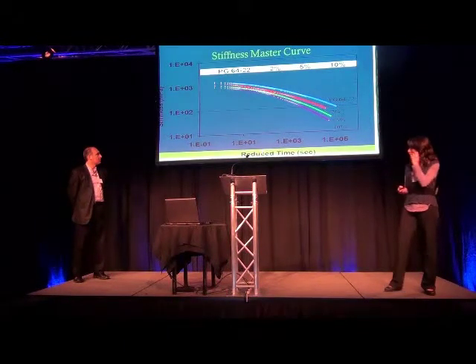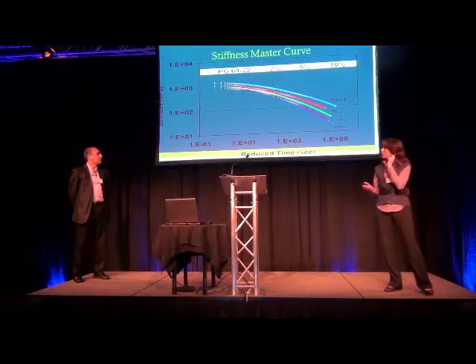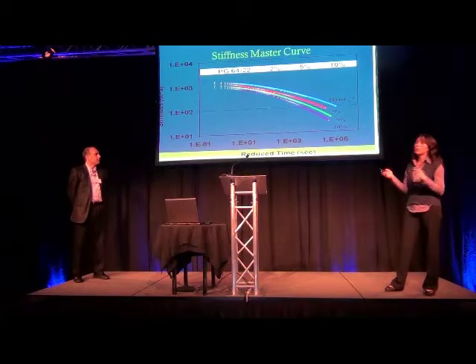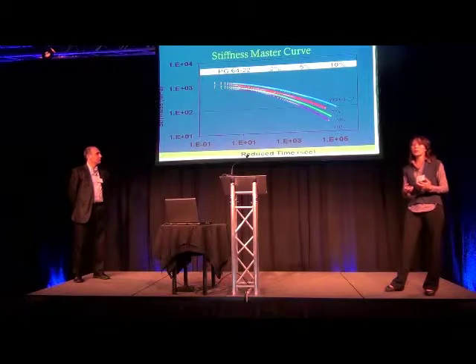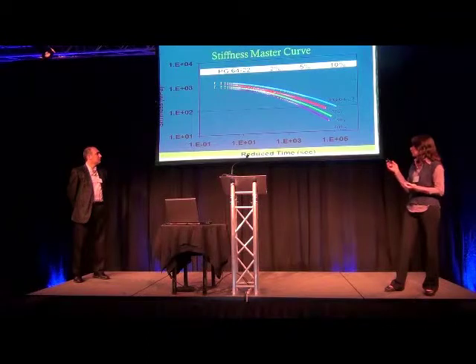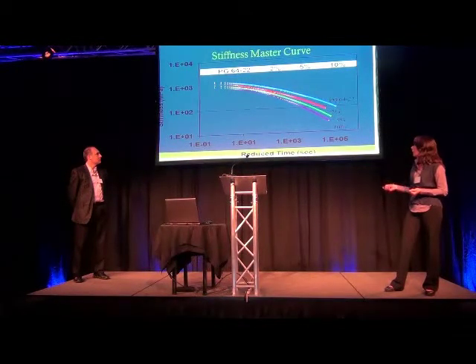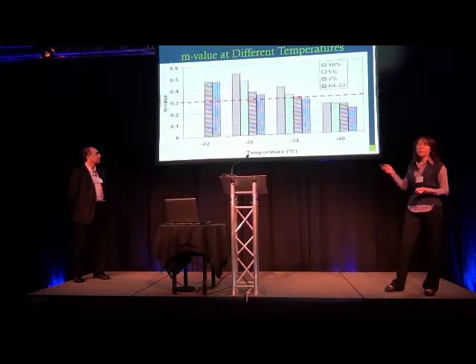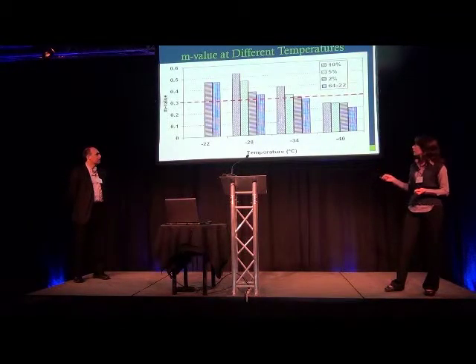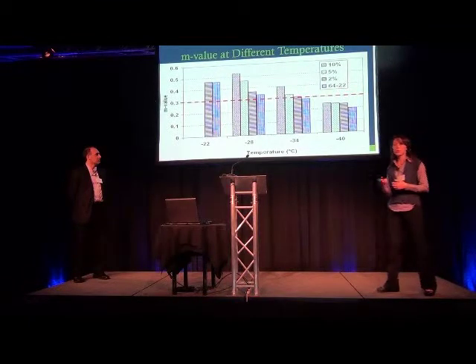We also look at the stiffness properties, and these are at different times, as asphalt is a viscoelastic material, so it is time and temperature dependent. So we look at different times or frequencies here, and you can see that the stiffness modulus keeps dropping. This is the control, and this is our 10% addition of the adhesive, the modulus dropping. We look at the m-value. This parameter here is basically a measure of how fast the material can release the load.